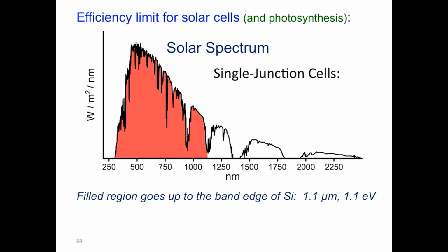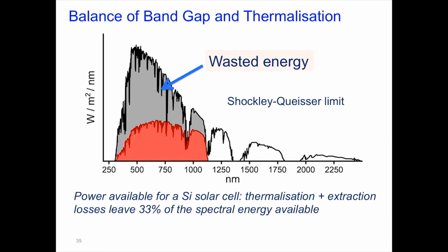So at a stroke, we had to make a choice as to where to draw the line, what part of the spectrum to throw away, and that's the wavelengths longer than the infrared. So we've done that. And then we start throwing more away. There's something we inevitably have to throw away due to entropy factors that the Shockley-Queisser analysis showed some time ago. But there are other losses. So what we actually can use is the red shaded curve, and the stuff that's wasted is the difference between the grey and the red.